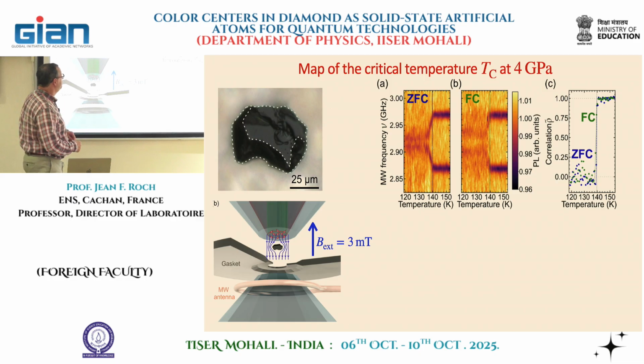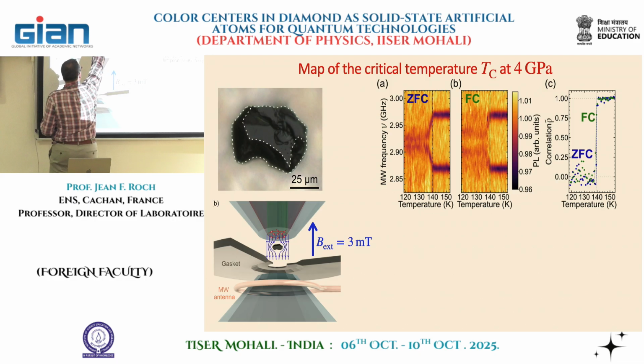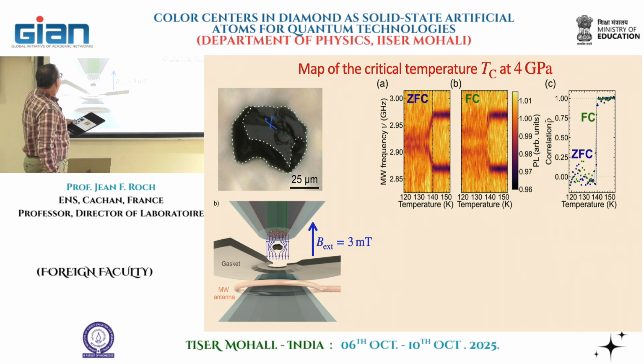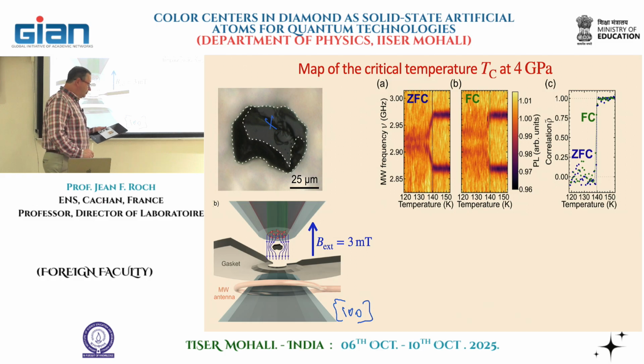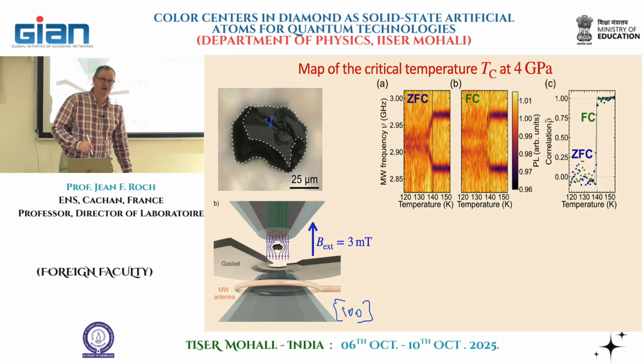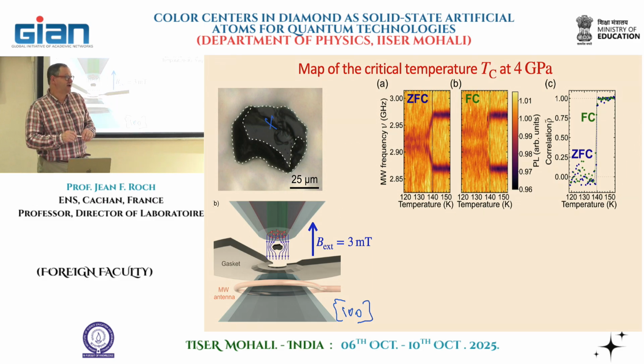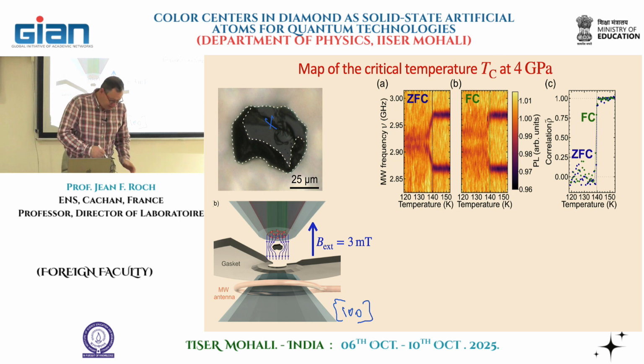We can do the experiment on one point, like, for instance, choose one point above the superconductor. Let's say, I think it was something like here, if I remember well. And we measure, like before, the evolution of the ESR, of the magnetic resonance of the NV center for the 4 families, with a small magnetic field of 3 millitesla applied along the z-axis, and the z-axis is also the 1, 0, 0 axis of the diamond. So we have 2 ways to do the experiment. The first one is called zero field cooling, and the other is field cooling. We'll try to explain the difference later on. In these 2 regimes, we observe the same behavior.